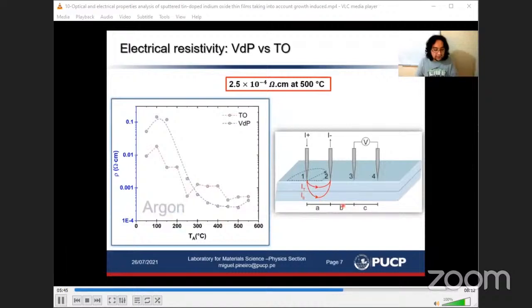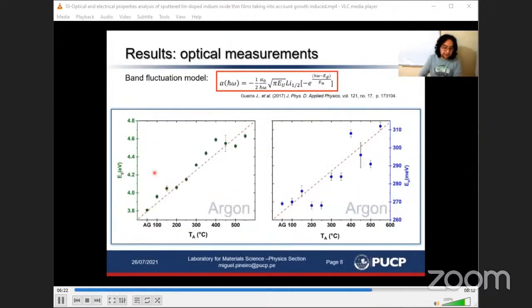So as the electrical current has a radial behavior, we take the two layers as if they were parallel resistors. In this way, we calculate the electrical resistivity from the transmittance measurement and compare it with the electrical resistivity measured by the van der Pauw technique, as shown in this figure. We can see both resistivities present the same behavior. The lowest electrical resistivity value was obtained at 500 degrees centigrade. Now, this figure shows the energy gap on the left, and the figure on the right represents the Urbach energy. Both are as a function of the annealing temperature.